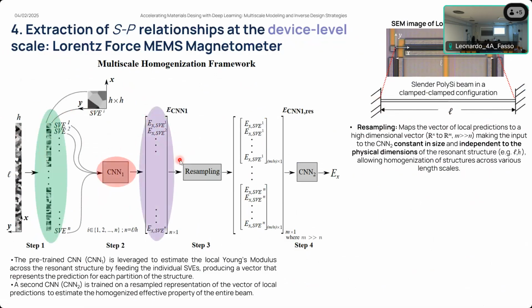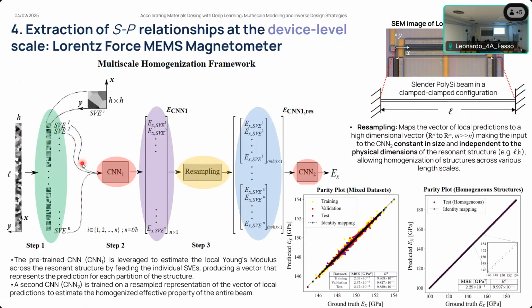So we obtain a vector of local predictions for this beam structure, and then we can perform a resampling operation where we map this vector of predictions to a higher dimensional space in order to obtain a new vector that accomplishes 2 functions. The first one is that it makes the input to the second CNN constant, and importantly, makes this input independent of the actual physical dimensions of the resonant structure. And through this operation, we are able to use this framework to perform homogenization across various length scales. In this case, again, we obtained a very good agreement between CNN predictions and ground truth values, achieving even an average relative error lower than 0.5% for an additional test set that was assembled, characterized by very different features compared to the data used for training the CNN.